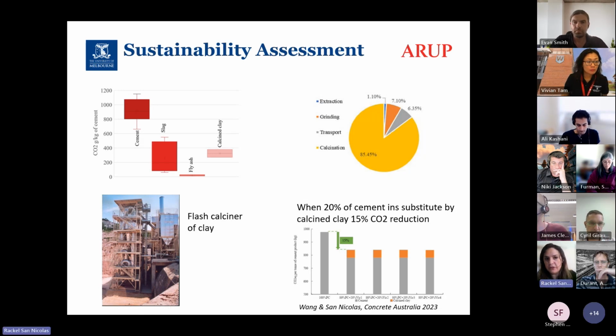Just a little bit more information on the sustainability of calcined clay. Most of the embodied carbon of the calcined clay is due to the calcination transformation. I put here a picture of one of those calciners, and you can see that 85% of the embodied carbon of calcined clay is actually due to the calcination. It's not transport, it's not grinding, it's not extraction. It's really the calcination. However, we are still in the low end within the range of slag and fly ash.